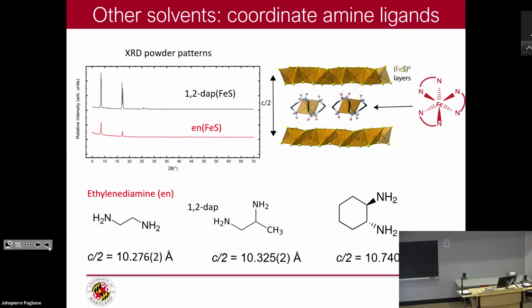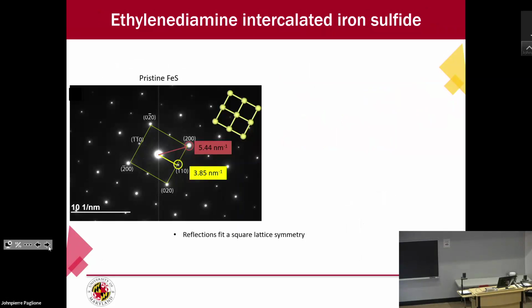So in any case, this is an example of an iron sulfide that's structurally similar to the iron selenide superconductors, where we're able to intercalate these different amino groups that we use for solvothermal synthesis. So it's not just the actual solvent, the medium, but it's actually also participating and going into your structure. For us, we want that. In some cases, maybe you don't want that. You don't want the solvent to go into your crystal structure. And if you pull out the solvent, the crystal actually falls apart in many cases. And so you have to wonder if it's good or bad for you.